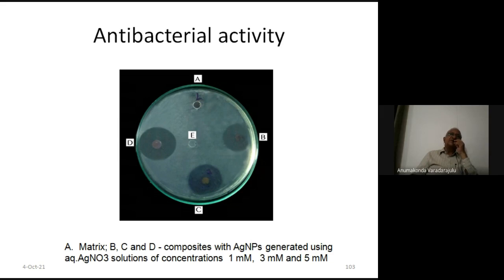But we tested that after several washings, the particles stayed inside because the particles are held by the matrix. There are OH groups in the matrix cellulose which have negative charge, and this metal nanoparticle has positive charge. As a result, there is an electrostatic attraction between them, so they are held permanently by these electrostatic forces inside the composite. So the coming out of these particles into any food material is very minimum. It may be in tolerant stages only.